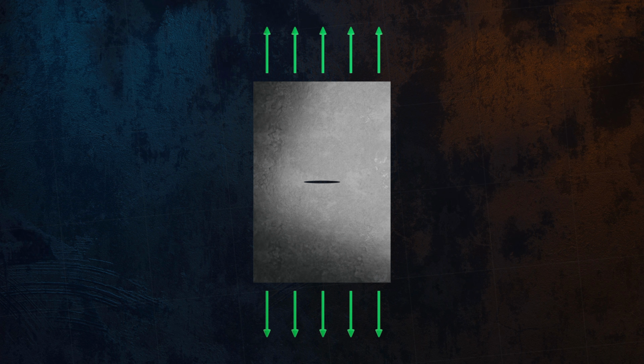We've seen that linear elastic fracture mechanics compares the stress intensity factor with fracture toughness to tell us whether a crack is stable for a given applied load. But if the applied load varies over time, even a small, stable crack can grow incrementally, eventually reaching a critical size where it becomes unstable and suddenly propagates to failure. Paris's law is the key equation used to predict the fatigue growth of cracks.